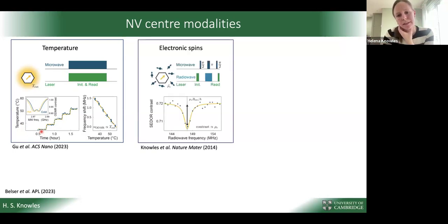Then we can also look at doing this nanoscale ESR that I mentioned briefly in the beginning. The idea is that we apply not a continuous excitation, but a so-called spin echo sequence on the NV center, where we create a superposition state, then exchange populations halfway through, and read out at the end. The trick is, simultaneous to this central pi pulse, if we also target another spin species which is nearby, we will selectively introduce noise from only those spins into the spin echo signal.